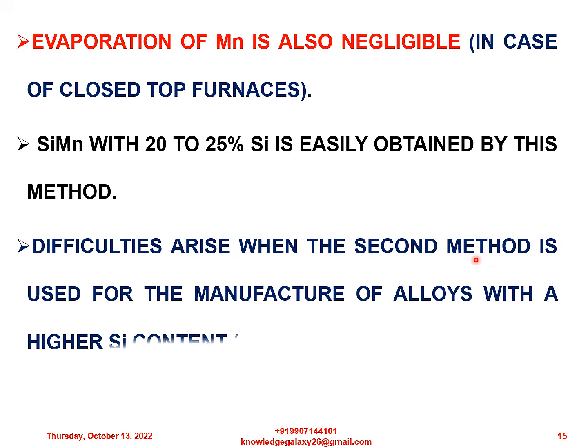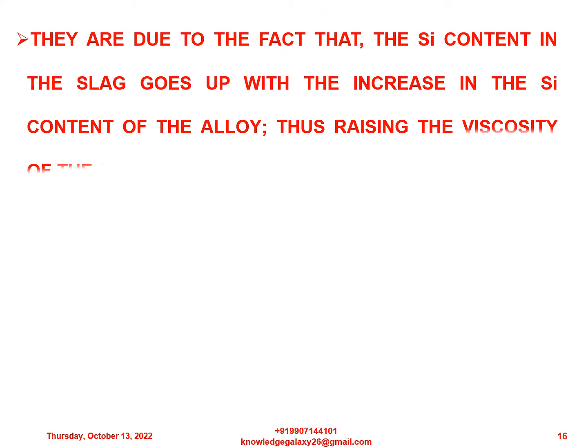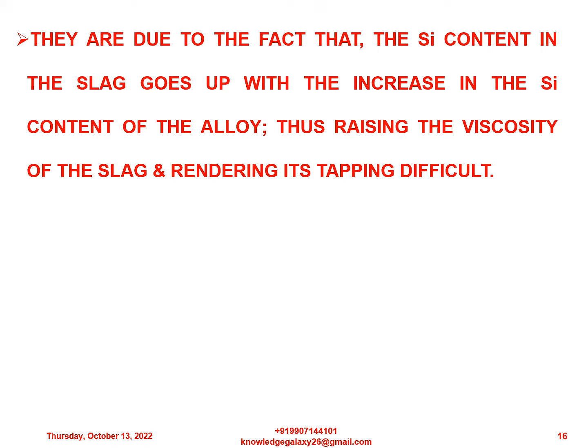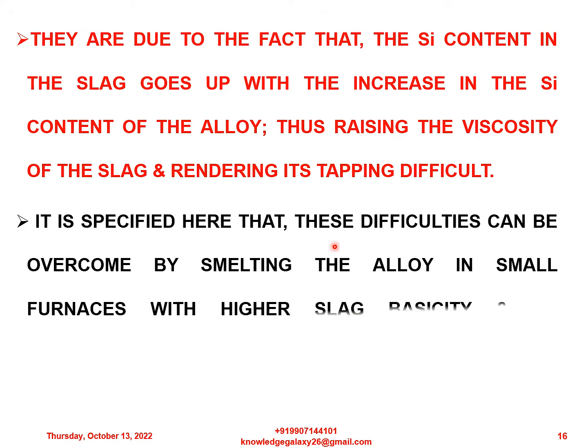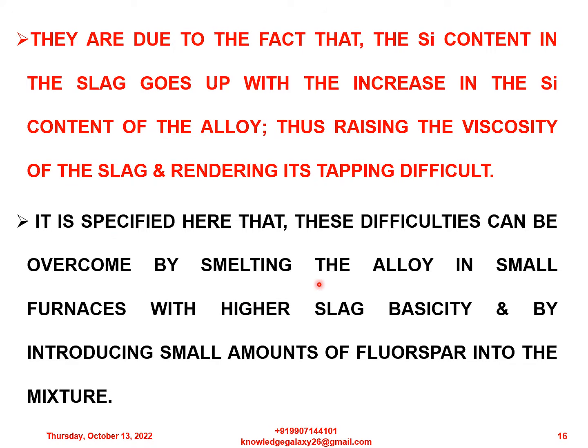Difficulties arise when the second method is used for the manufacture of alloys with a higher silicon content, that is above 25%. They are due to the fact that the silicon content in the slag goes up with the increase in the silicon content of the alloy, thus raising the viscosity of the slag and rendering its tapping difficult. These difficulties can be overcome by smelting the alloy in small furnaces with higher slag basicity and by introducing small amounts of fluorspar into the mixture.